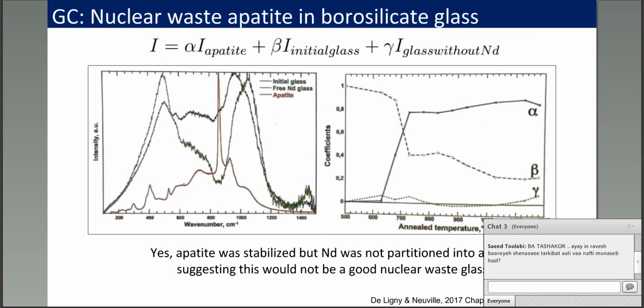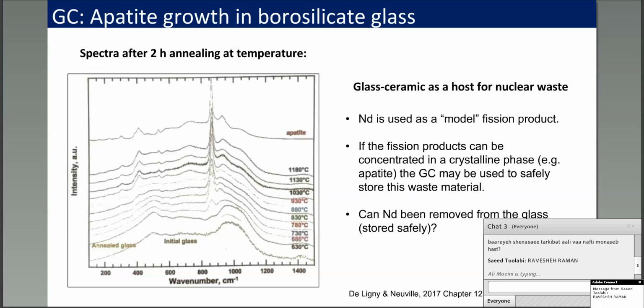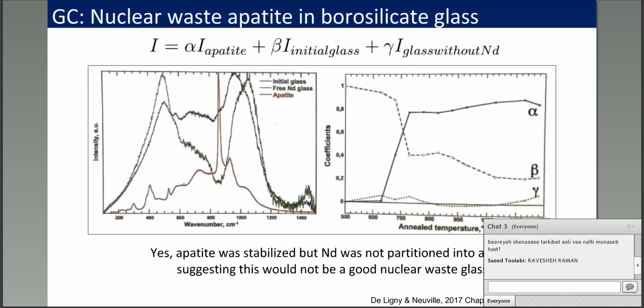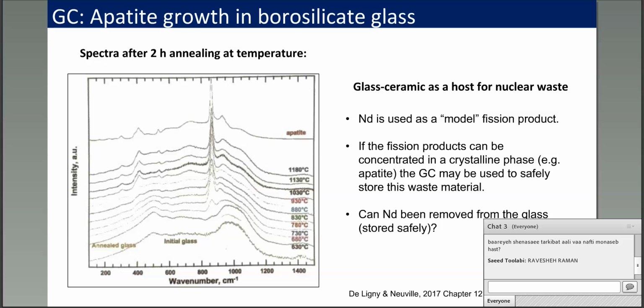This is a very broad question, so let me answer in a couple different ways. I didn't have time to present this example, but here is a borosilicate glass where they've added phosphate and neodymium in trace amounts to model the fission products of nuclear reactors, for example. And what they wanted to do was to get a crystal phase to precipitate and stabilize, and that would host the fission products, and neodymium in this case is their example, and remove it from the glass so that as the glass broke down and crystallized, any of the fission products or neodymium would be trapped in the crystalline phase and not be released into the environment. So I don't know what the concentration is of neodymium in this sample. I forget off the top of my head, but you're talking sub-percent level.